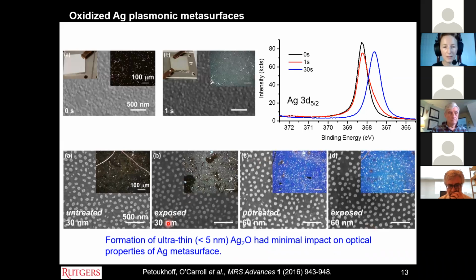Another student of my group who graduated a number of years ago, Chris Petoukhoff, looked at these oxides. As I mentioned, he looked at the thickness of these oxides as well as their effect on the optical properties of metasurfaces. And they don't really change the optical properties very much when we expose nanostructured silver. These are with 30 nanometer silver particles or 60 nanometer silver particles. You can see that the scattering is slightly increased when we partially oxidize the silver surface.